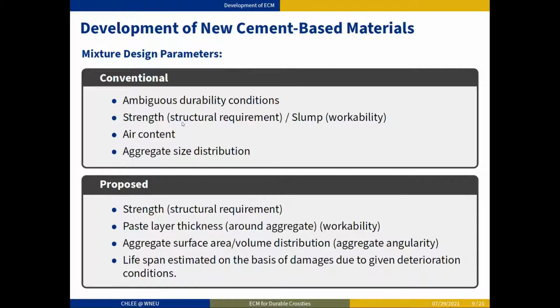Also, the strength, which is a structural requirement, and slump for workability were the design parameters, and air content, related to the workability and the freeze and thawing performance, was one of the design parameters. And maximum aggregate size was a design parameter. However, that number is somehow based on the aggregate size distribution.